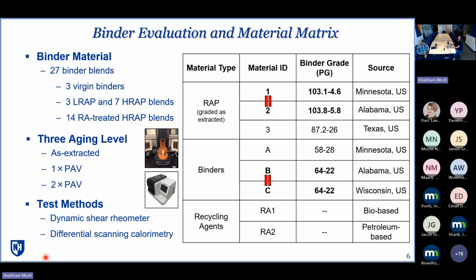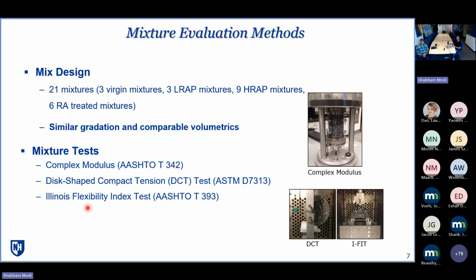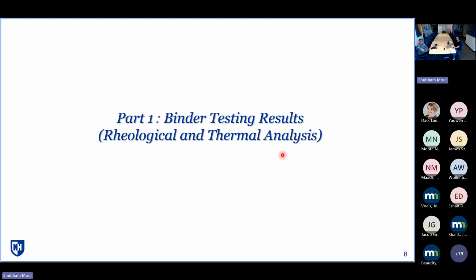And as discussed, we evaluated these two test methods in this presentation. On the mixture evaluation side, we generated 21 mixtures: 3 virgin mixtures, 3 low RAP mixtures, and 9 high RAP mixtures, including 6 RA-treated mixtures as well. One thing we took care of is that we ensured similar gradation and comparable volumetrics for all these mixtures to avoid variations from those sides, and the same aggregate source was used in all the mixtures. The mixture tests are shown in picture form here as well.